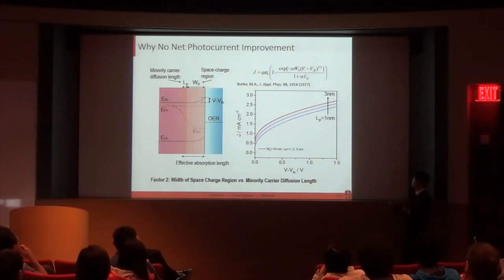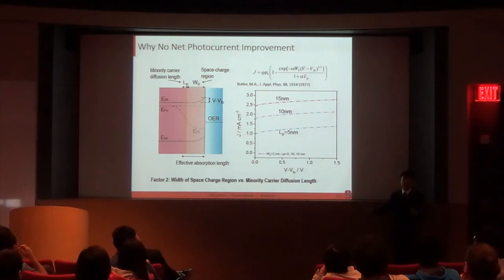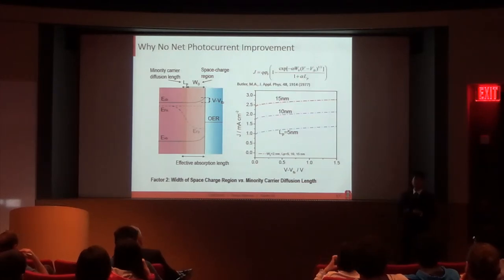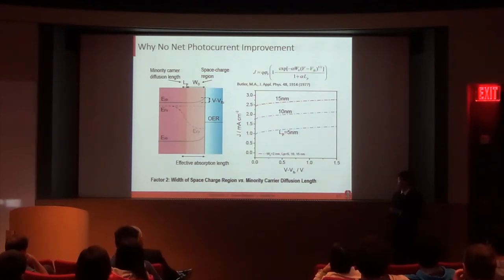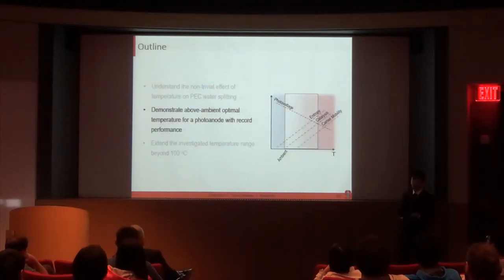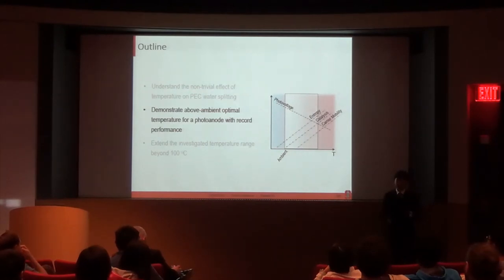And if I intentionally increase this number to be longer than the space charge region width and still vary it by a factor of 3, then we saw a much more significant improvement in the photocurrent. So that tells us we should choose a material that has a longer minority carrier diffusion length as compared to the space charge region width. So keeping these two factors in mind, we carefully selected a second material system and explicitly demonstrated that thermal energy could be a beneficial and efficient way to improve its actual performance.